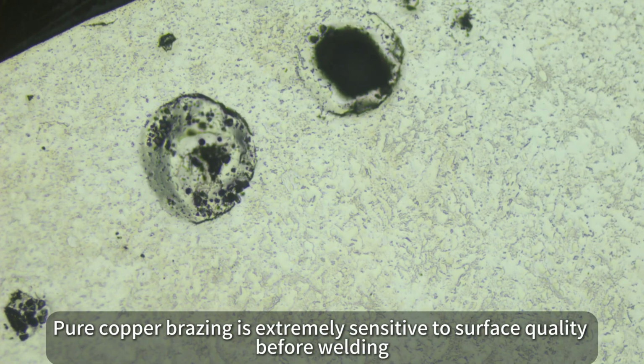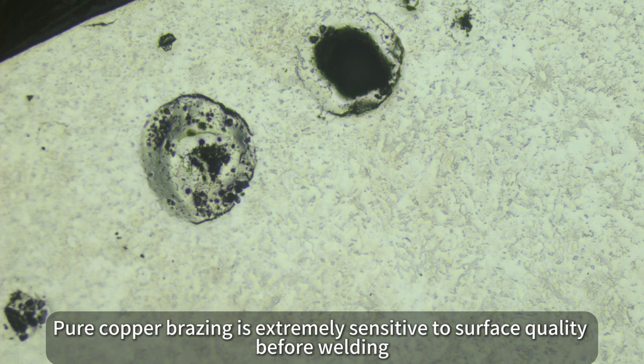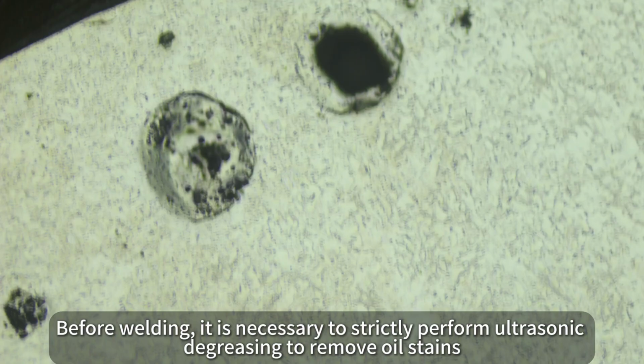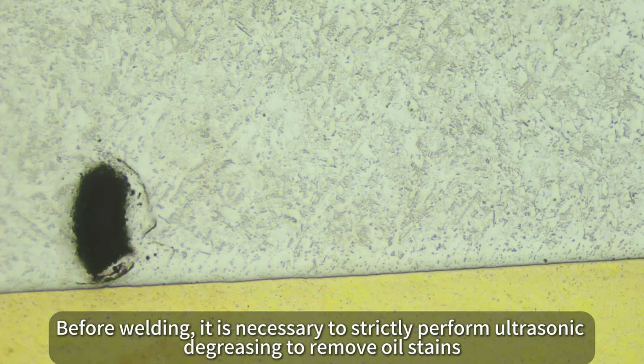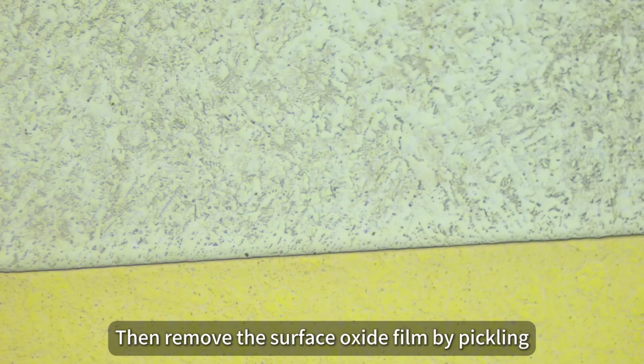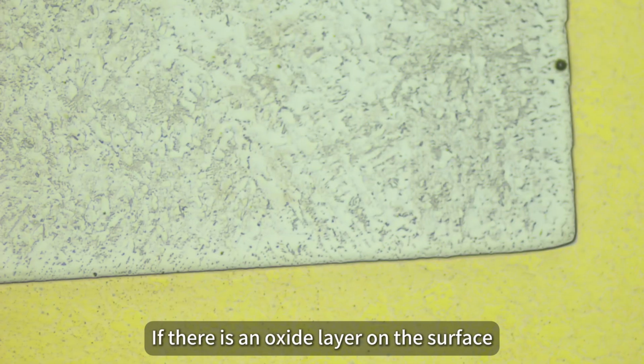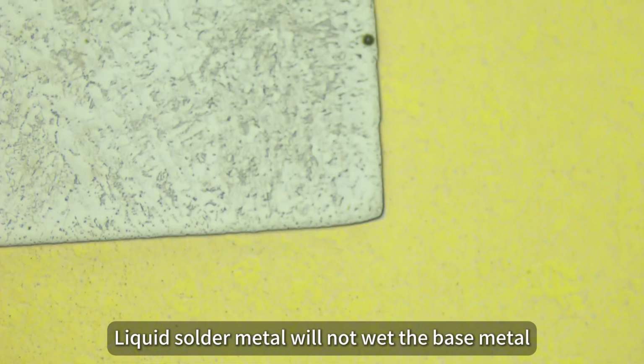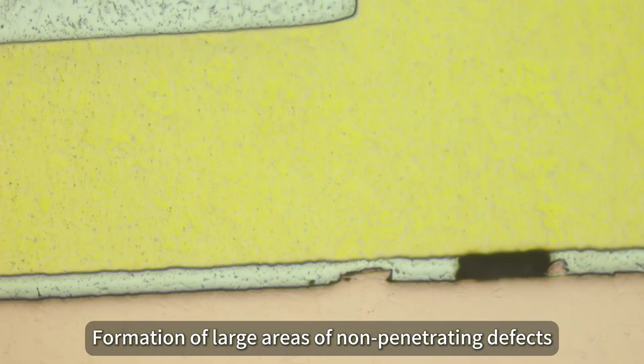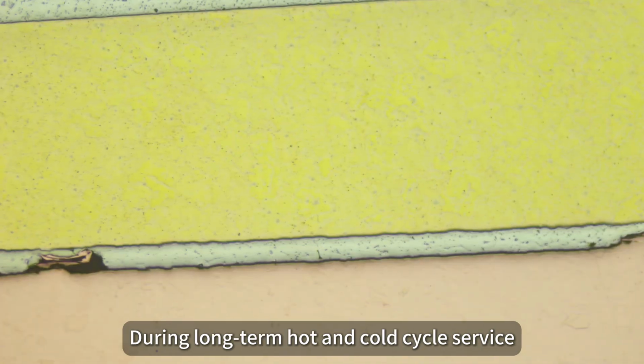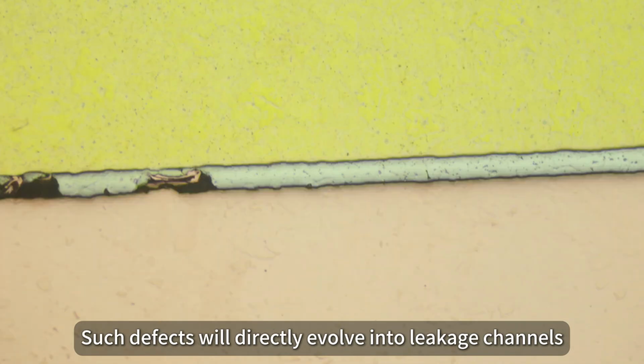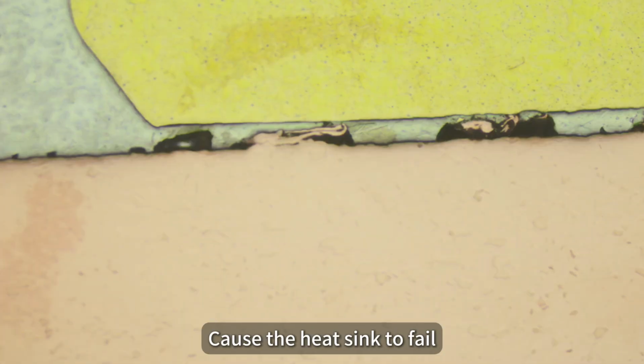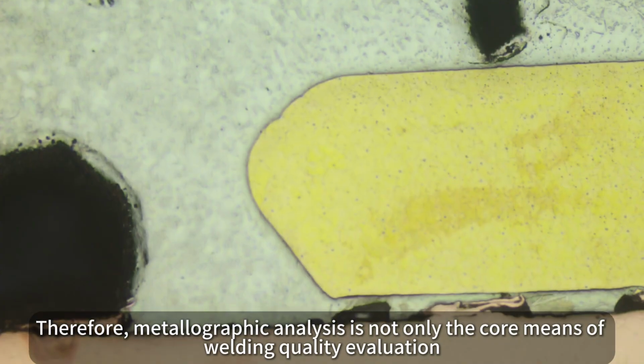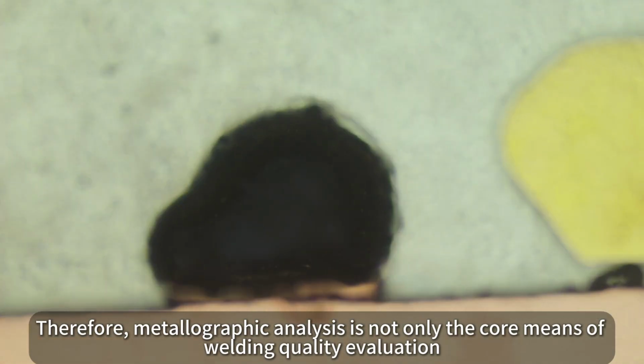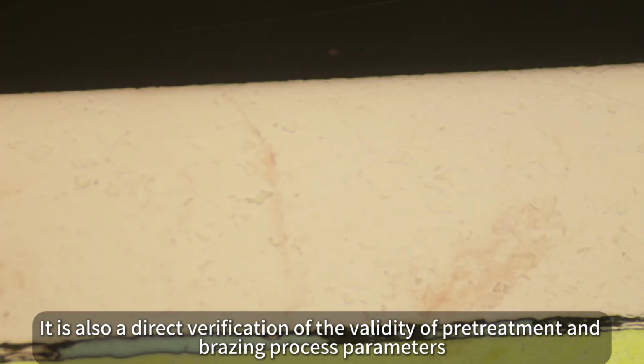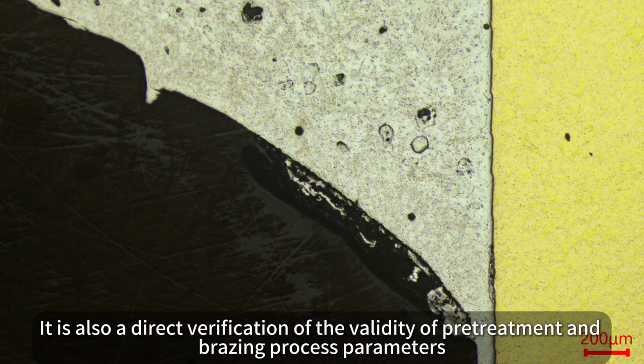Pure copper brazing is extremely sensitive to surface quality before welding. Before welding, it is necessary to strictly perform ultrasonic degreasing to remove oil stains, then remove the surface oxide film by pickling. If there is an oxide layer on the surface, liquid solder metal will not wet the base metal, forming large areas of non-penetrating defects. During long-term hot and cold cycle service, such defects will directly evolve into leakage channels and cause the heatsink to fail. Therefore, metallographic analysis is not only the core means of welding quality evaluation, it is also a direct verification of the validity of pre-treatment and brazing process parameters.